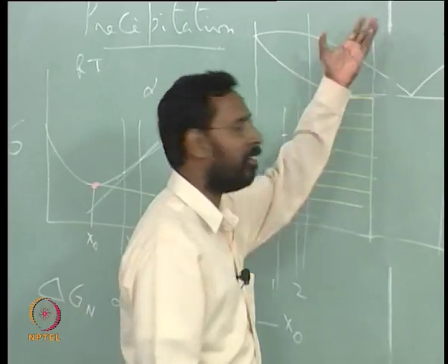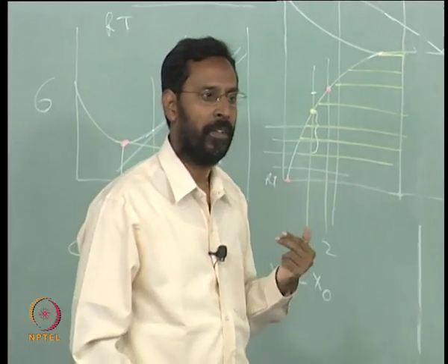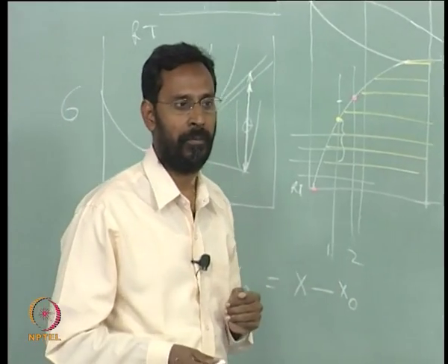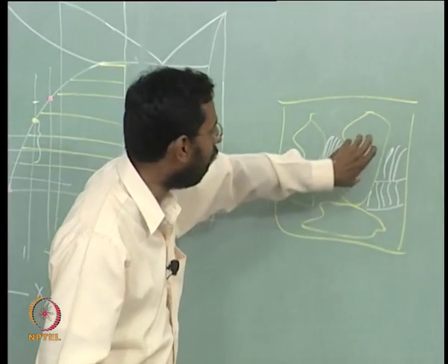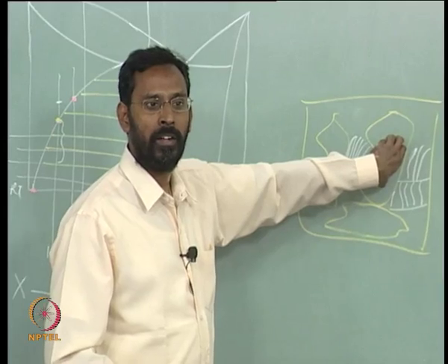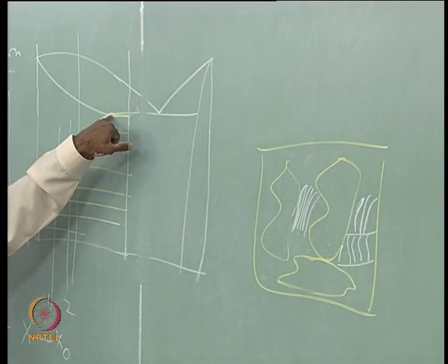And when I am heating this back, now both the thetas start dissolving: the theta at the dendrite boundaries and the theta within the eutectic mixture. Both of them start dissolving, and as a result, once you reach this temperature, you will have some theta left out. And now when you quench it, because the theta has dissolved, these dendrites become richer again in copper to the extent of what it would have had just after the eutectic reaction.